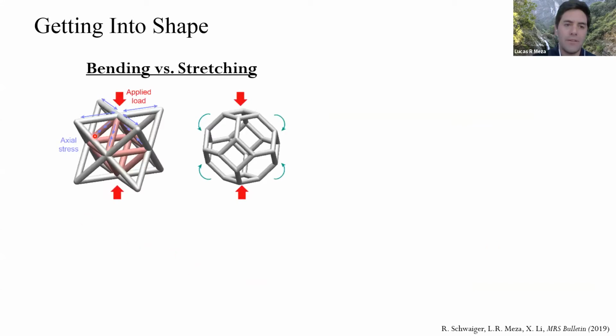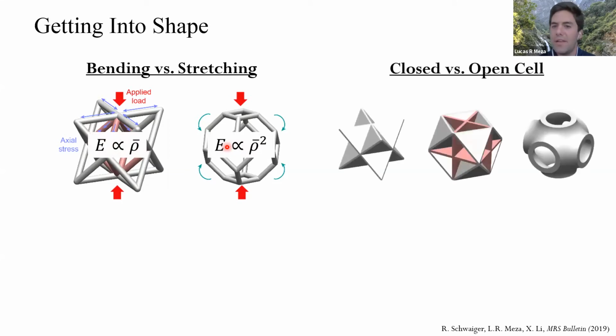A lot of the work I had done early on was on lattice structures. There's this kind of classical idea of bending versus stretching architectures, where this sort of octet truss would carry load in tension and compression and carry load more optimally than this tetrakaidecahedron, which carries load primarily in bending. It turns out to be a little bit more complicated than that, which I'll talk about later in the talk. In general, though, people have found that lattices don't scale optimally.